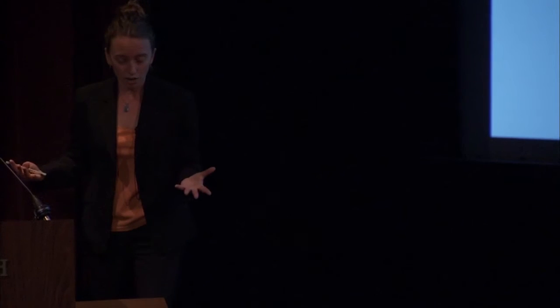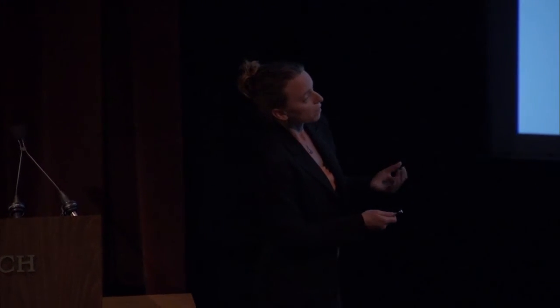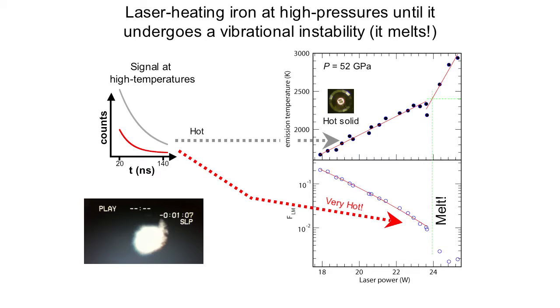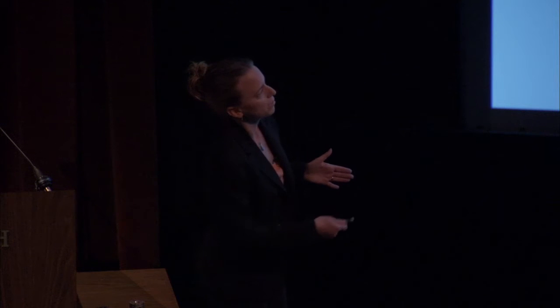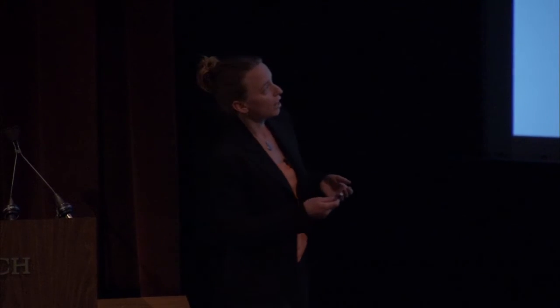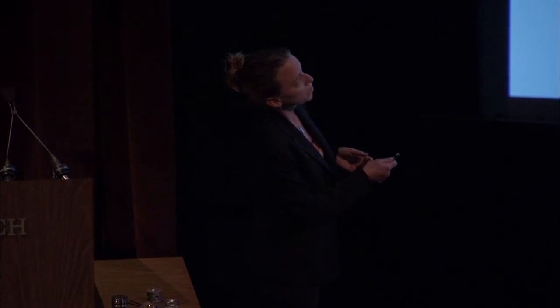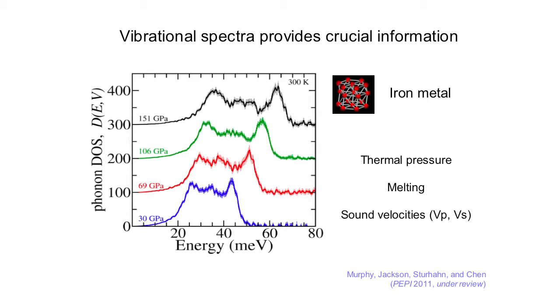And this is where the material melts. So what we have done here is that we have just measured a melting point of the iron metal using a new method. So this particular method hasn't been used before. And we also have a tracking of the vibrational properties. And so this is something that we're developing right now. So this is very new. And we're able to determine the pressure accurately because of those vibrational measurements that I just showed here. This is able to tell us accurately what the thermal pressure of the whole system is at these high temperatures.